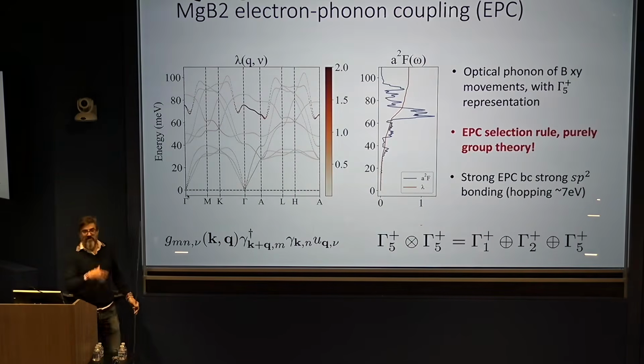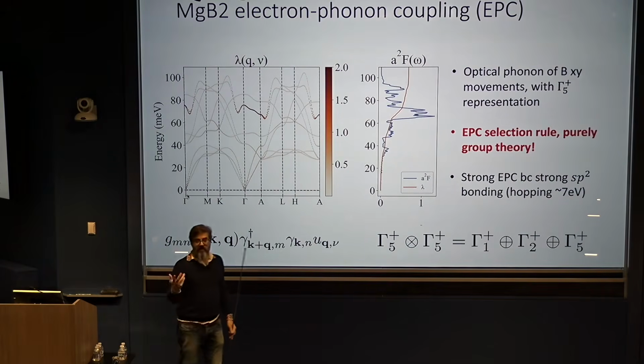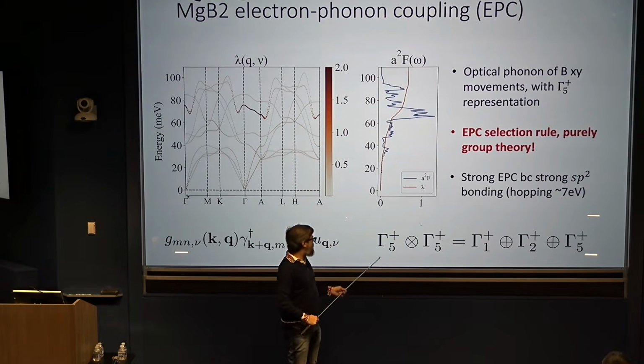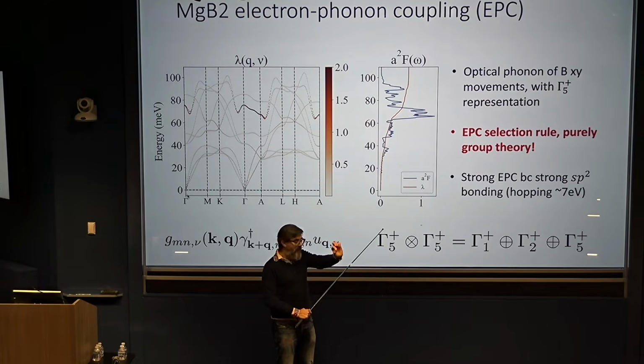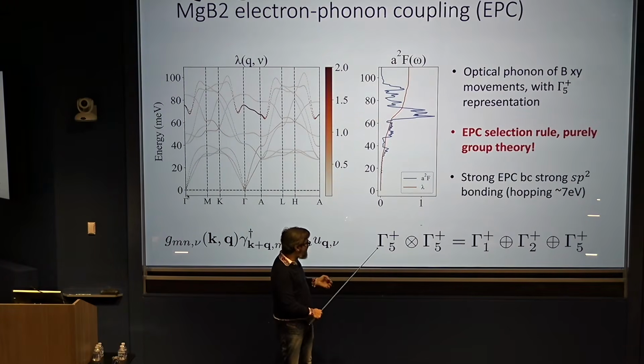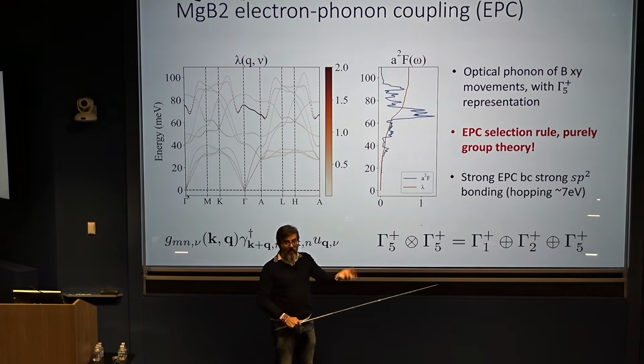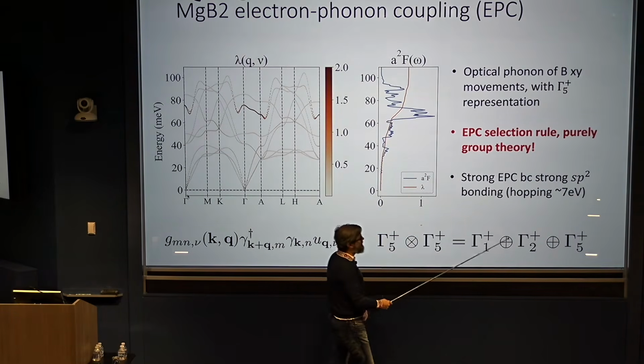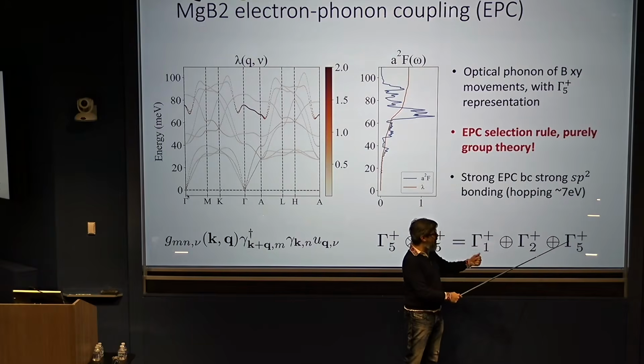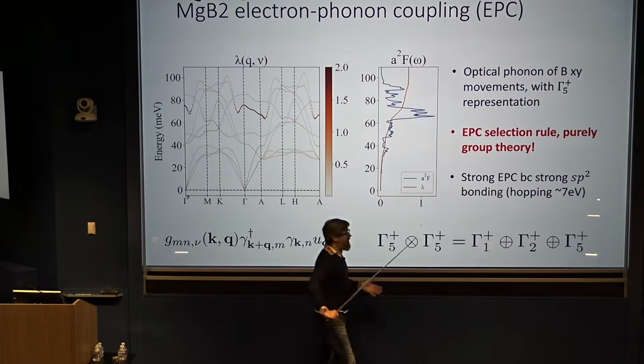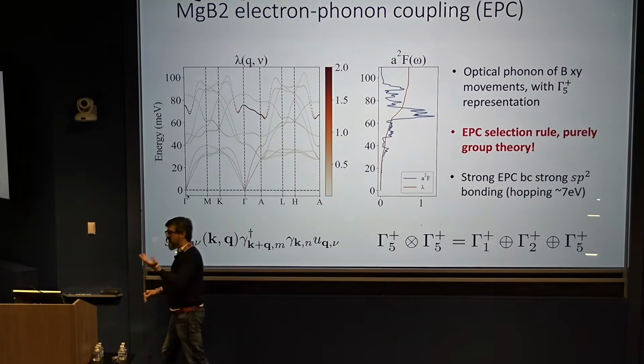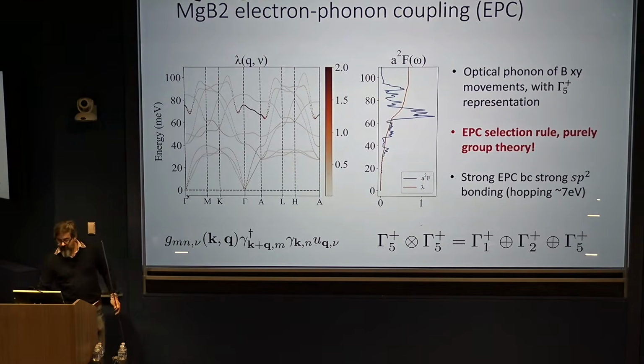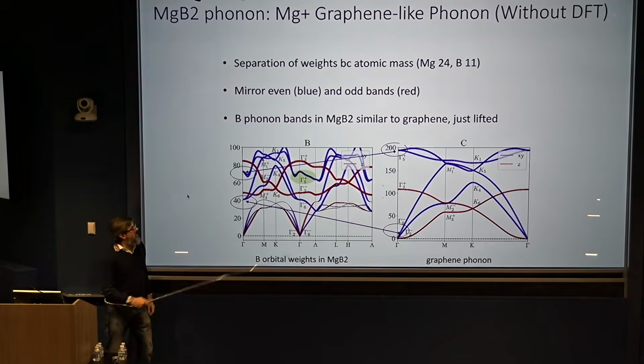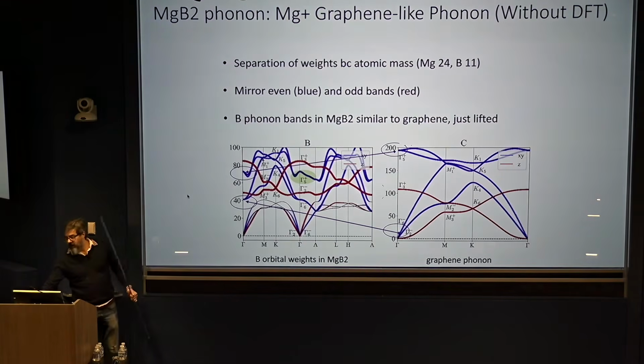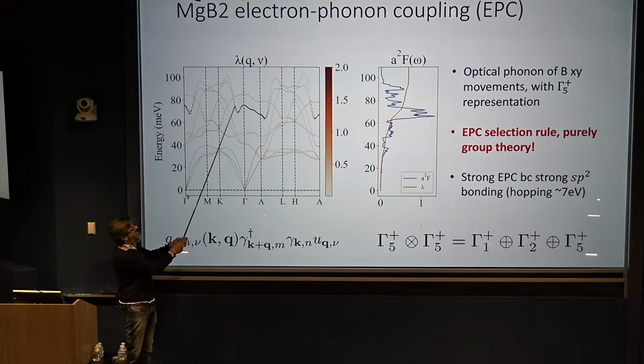But there's a very easy group theory way of understanding which one is important, because the representation of the Fermi surface, of the double vortex, is gamma 5. I have 2 electrons, gamma 5, gamma 5. I have to couple them to a phonon. I want to know which scalar comes out of it. It turns out the only one that can couple, so I have phonon, electron, electron, is gamma 5, gamma 5, gamma 5 will give you a scalar, so it is the gamma 5 phonon that couples. That phonon is this guy, and it's actually the same guy that shows up here.